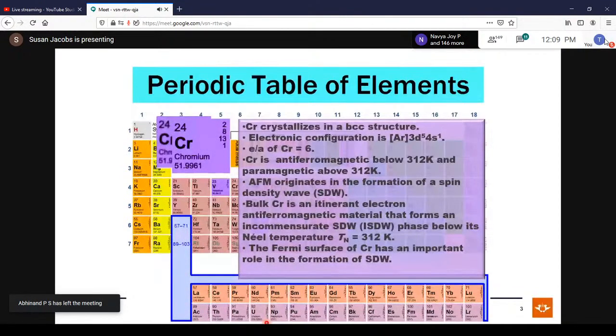It crystallizes in the body-centered cubic structure. Its electronic configuration is argon 3d5 4s1. The electron to atom ratio of chromium is 6. It is an antiferromagnet below 312 Kelvin, and it's a paramagnet above 312 Kelvin. Now, the antiferromagnetism in chromium is established by the formation of a spin density wave. I will explain this shortly.